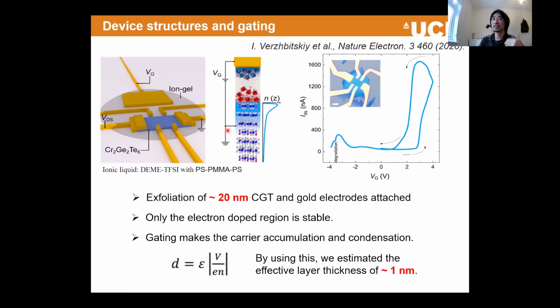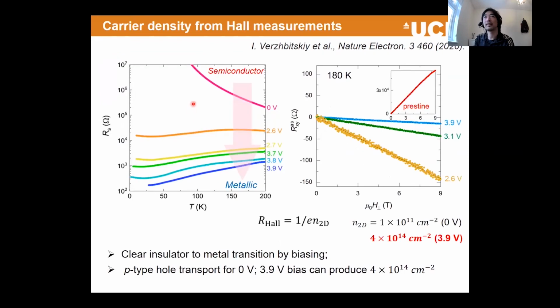So just starting with 20 nanometer, but effectively we create a monolayer two-dimensional electron gas by the gating. So that's an interesting point. Right, so then this is the resistance versus temperature. You can see that at 0 volt voltage application, this is more like semiconductor insulator behavior, but once you apply high voltage, then you can see that this is the metallic behavior, which is great.